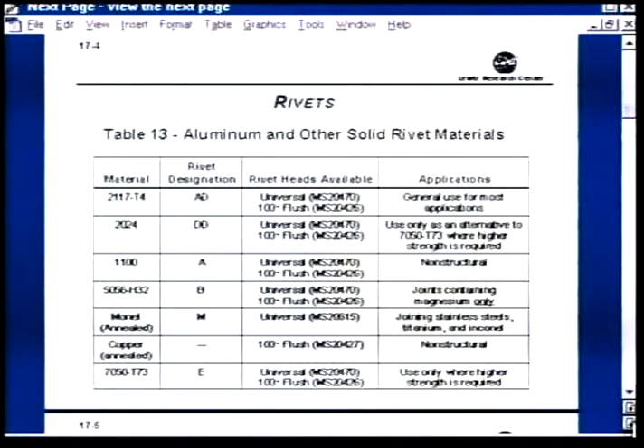Of course, the aircraft industry uses a lot of the ADs and DDs, which are the MS 20426 and 20470. The ADs are used normally up to a 5/32 diameter, and they can be readily formed at room temperature. The DDs, if they're made out of 2024, they have to be kept in an ice box until you're ready to install them, because you can only cold work them when they're down around 0 degrees without cracking them.